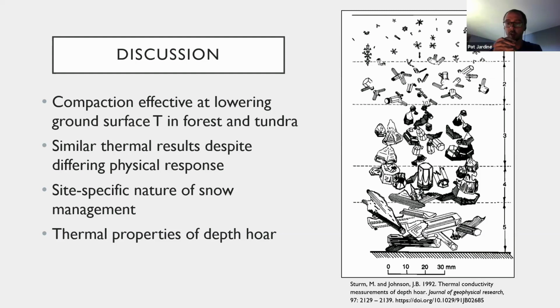Thermal conductivity generally increased with metamorphism as the snow crystals grew, right up until they reached stage 4, in which case there's a dramatic drop in thermal conductivity. At this stage, the crystals have grown large enough that they begin to spread apart, and they're only loosely connected by thin contact points. So there's not really much room for conduction. This caused the thermal conductivity to be reduced to as low as below 0.05 watts per meter Kelvin, and that was the really low thermal conductivity that was on the graph earlier in the slides.